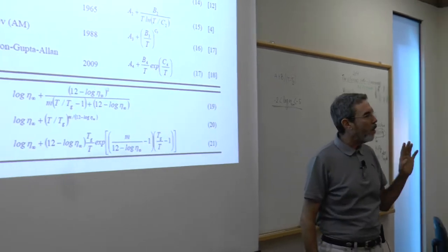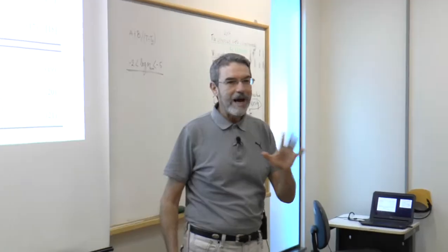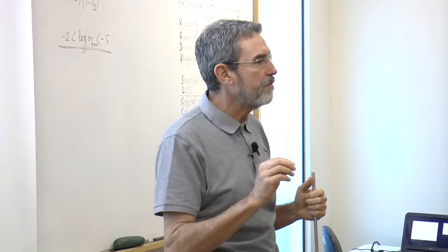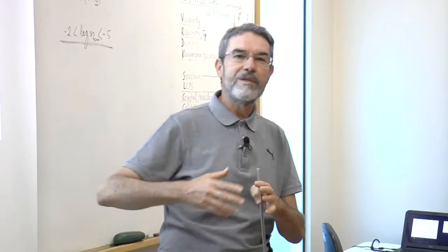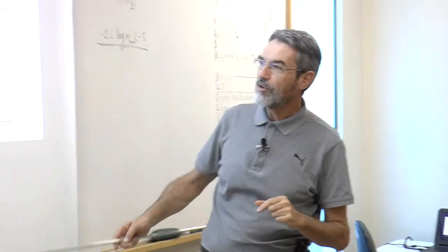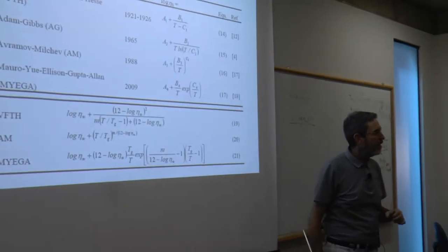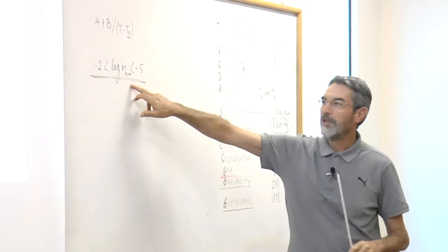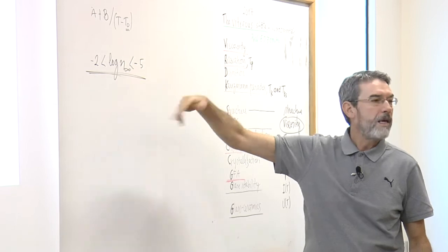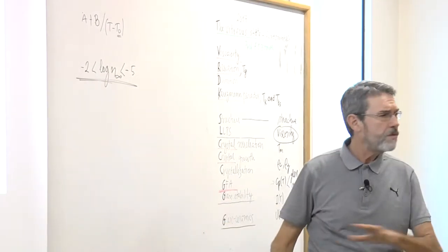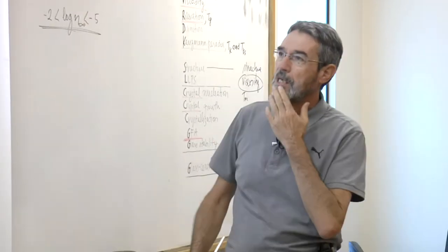So I gave you some homework to do. We are going to discuss this after the class. I hope you're able to fit some of these viscosity curves to the glass that you have adopted. Each student has adopted a different glass. They are going to work with the same glass throughout this course. But I'm interested in knowing what sort of values of eta infinity have you gotten from your fits. They have to be within this range here, -2, -5 in Pascal second, when the viscosity is written in terms of Pascal second. Most fits give values in this range here.